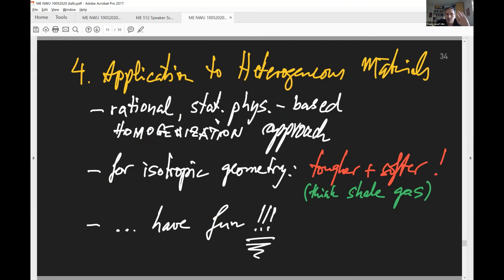Finally, the application to heterogeneous material here, which I showed you, it's rational. It's really based on the heat of bond rupture. So it's all about the dissipation which you release here. So I think there's an approach now in place which allows us to address what is beyond a particular case, the homogenization of fracture properties. I only showed you for the isotropic geometry. Tougher and softer is the best one here. And gas shale is exactly the material which I think about, because you have the kerogen in there, which is softer, but it deforms a lot and it makes this whole thing extremely tough.